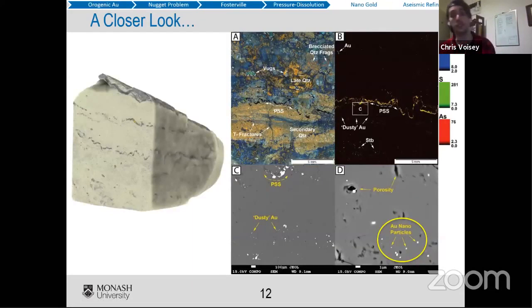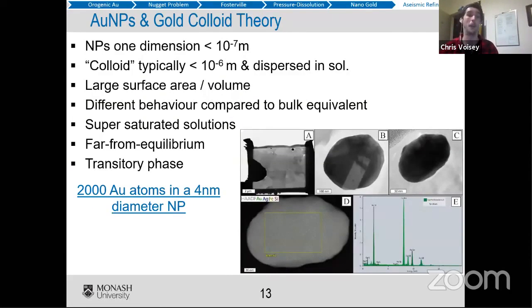So we took a closer look. We wanted to do CL to look at the quartz generations. Looking at the CL image here, this black seam is our actual pressure dissolution seam. That's a little wall rock selvage, so it's mostly shale and graphite. Then we look under the microscope and see a little bit of gold, these little dusty gold seams. We zoom in further, on this little square, and we find really, really fine grained gold. We've seen gold that was notably much smaller than a micron, so nanoparticle gold. So then we started looking at gold nanoparticle and gold colloid theory. So what is a gold nanoparticle and how do they work?